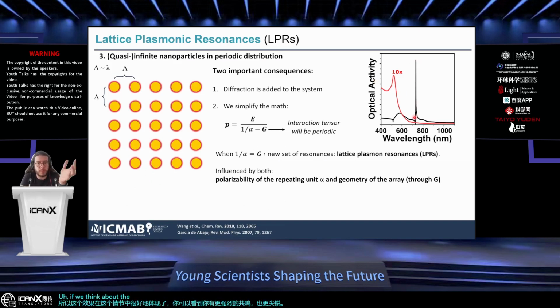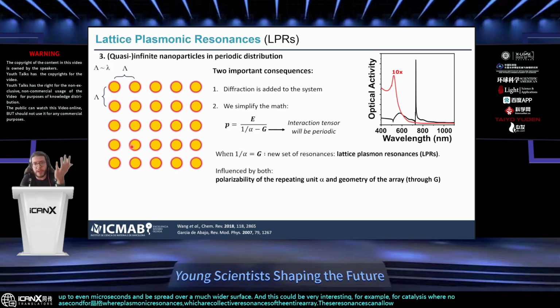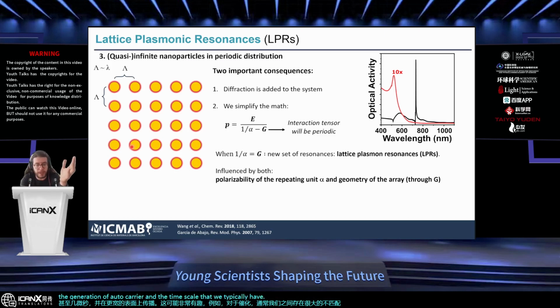If we think about the Heisenberg principle, a much sharper resonance also means a much more long-lived resonance and also much more delocalized. While localized resonances typically decay on the order of picoseconds, lattice plasmonic resonances, which are collective resonances of the entire array, can last up to even microseconds and be spread over a much wider surface. This could be very interesting, for example, for catalysis, where normally we have a big mismatch between the generation of a hot carrier and the time scale that we typically have for chemical reactions. So we basically have a very short time frame where we can do this electron transfer that we talk about between the nanostructure and the molecule that we need to perform chemistry on. While if we were able to use this lattice resonance, we would have much more time to do it.